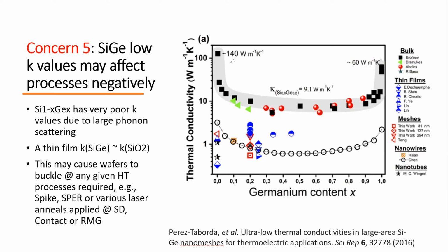That's amazing. What makes it even worse is that if you make a thin film out of it, it drops even further. If you have, say, a couple of nanometers, then you could be 100x off, become 1. And this 1 is like SiO2, all right? So this is how bad it is. A thin film SiGe is acting like a pure insulator now. So what's the problem? Well, if you have any high temperature process, like spike anneal, solid phase epitaxy regrowth, or laser anneal, at very high temperature, applied in the source and drain, like an RTA spike, contact for your SPER or your RMG process, laser anneal, your wafer could buckle.